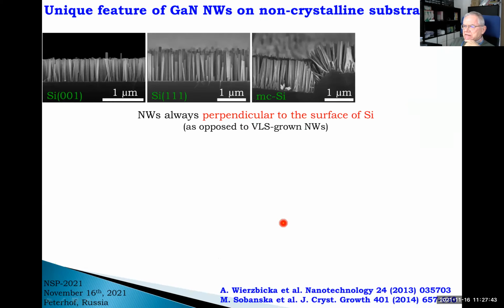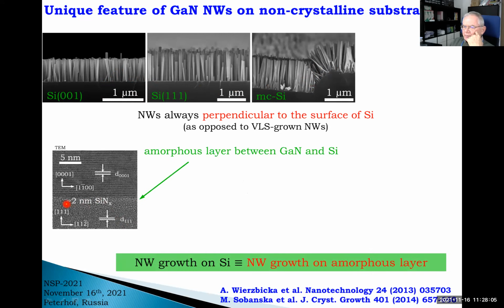A unique feature of these wires is that independently of the orientation of the silicon substrate underneath, whether this is 001, 111, or even multicrystalline silicon, we always have nanowires which are perpendicular to the surface, or to the local segment of the surface. And this is just because of the presence of the silicon nitride film in between. So these wires do not feel the orientation of the substrate underneath. In that sense, the term gallium nitride nanowires grow on silicon is not precise. Actually, these wires grow on amorphous silicon nitride, not on silicon.